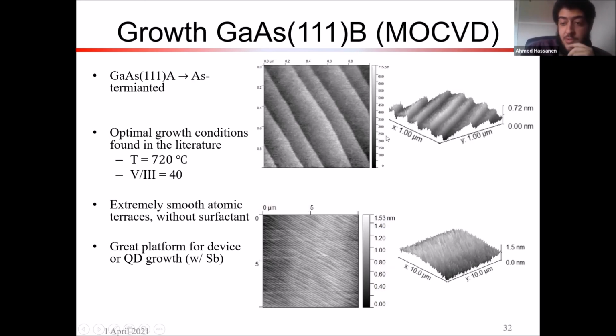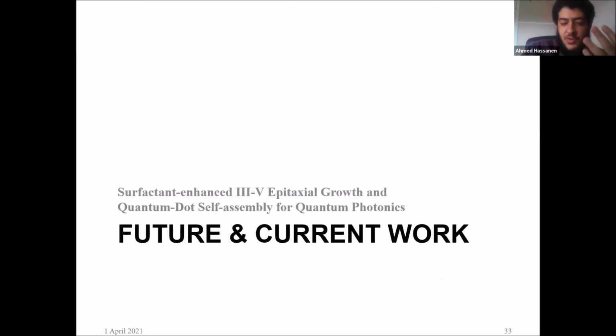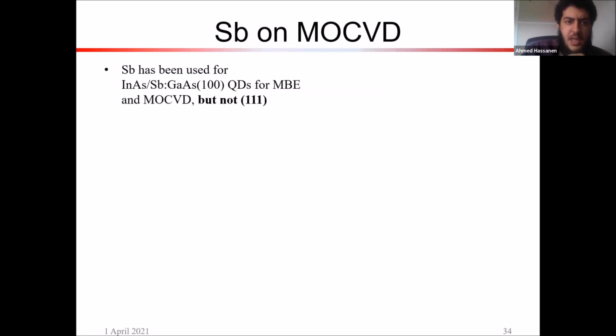Without even any surfactants. This was quite an interesting find, and this can be a great platform for device or quantum dot growth. So you can imagine now you can start to use indium arsenide with the surfactant to, instead of getting 2D layer growth, create 3D quantum dot growth, but this time on an actually good, smooth starting surface. And so just quickly to touch on some future and current work that I've been doing.